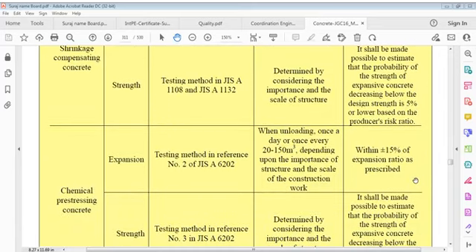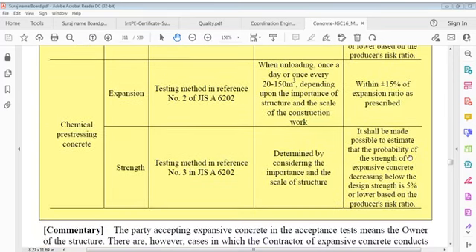For chemical pre-stressing concrete, the other item is expansion, within 15%. We must correspond to 15% of expansion ratio. For expansion, the testing method is an expansion test of chemical pre-stressing concrete, when unloading once a day or once every 20 to 150 cubic meters, depending upon importance of structure and scale of construction, within plus minus 15% of expansion ratio as prescribed.